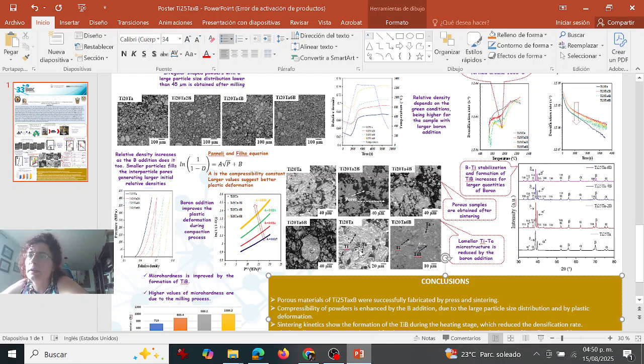All right. If we have a look at these images, for example, in here we have the sample without boron, and in here the sample with 6% of boron, and we observe that the lamellar titanium tantalum microstructure is reduced by the boron addition, because here we can clearly observe it, and in here only small lamellae are left around the sample.